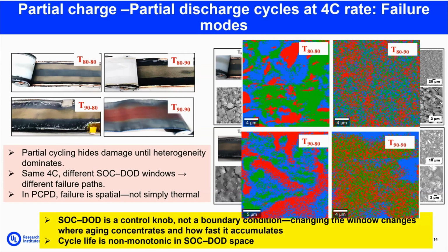Another thing is that these localized concentration gradients of the phases are also a driving force for lithium plating, where the current distribution changes, which actually drives the lithium plating mechanism. So lithium plating and stripping occur more in these three test conditions. That is because of the charge distribution variation. There are no homogeneous lithiation phases on the graphite surface at the end of cell discharge.